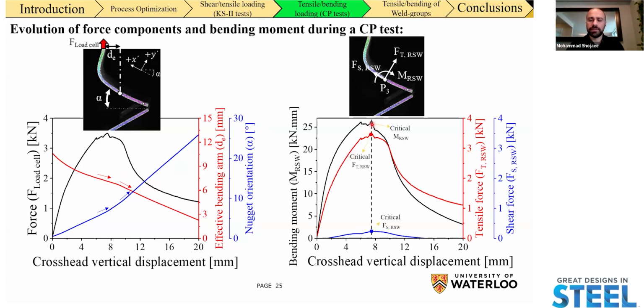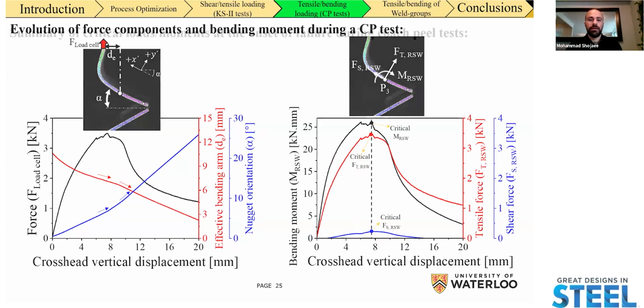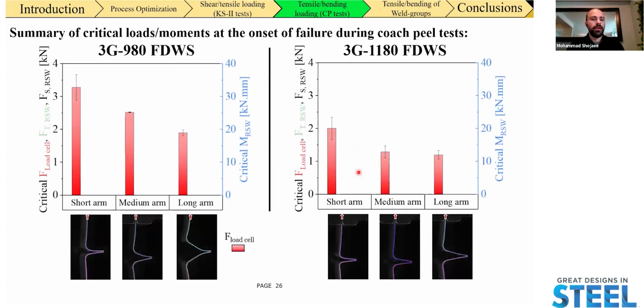We can extract the critical values of the bending moment and the tensile and shear load components and use them for calibrating our failure loci in tensile bending loading conditions. So let's take a look at the summary of these critical load and moment values at the onset of failure for different geometries of the coach peel test that we performed. And the red shows the peak load of the test.